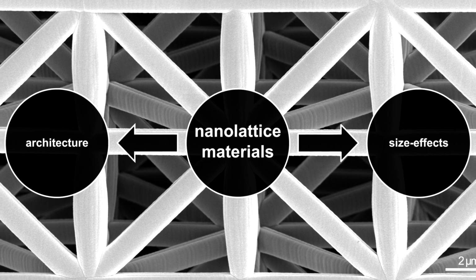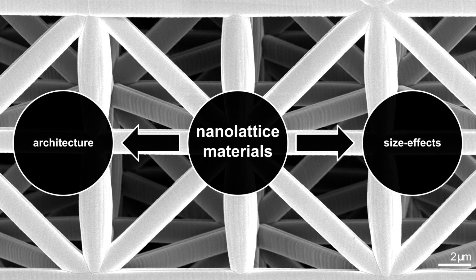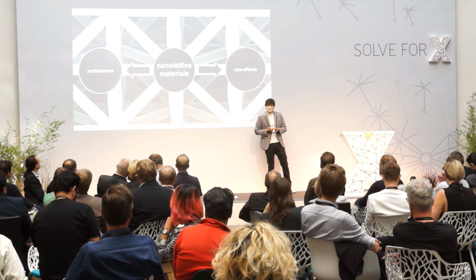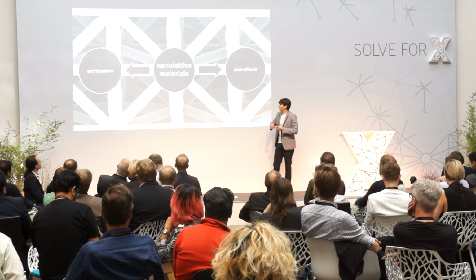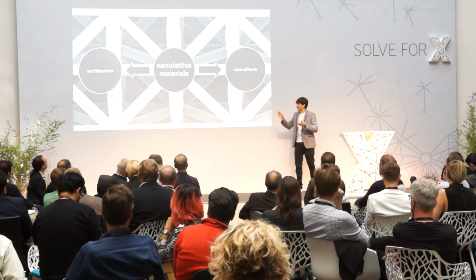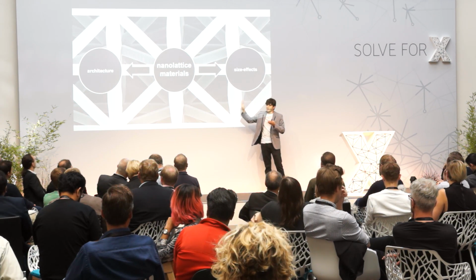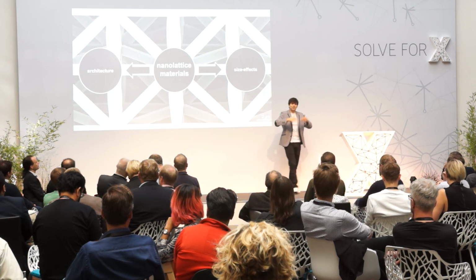And a way to do that is by nanolattice materials, which you can see here in the back. So what we got here is a stretching-dominated, optimized microarchitecture with single struts, which are only 1 to 2 microns in diameter. That means here we can apply walls, which are just a few nanometers thin, which makes them ultra-strong because of the small scale. However, by a periodic arrangement of such lattice cells, we could create much larger structures with that size effect being preserved.